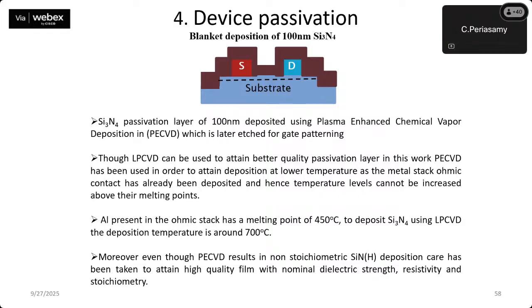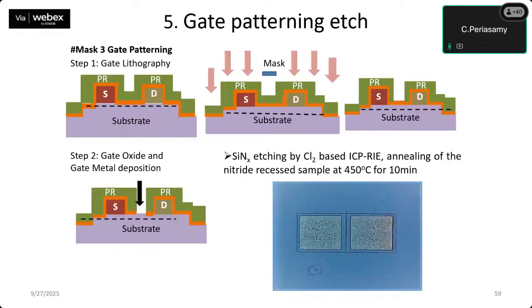So we have used that silicon nitride passivation layer, and the thickness of that passivation layer is 100 nanometer. As I told, we have used plasma enhanced, low pressure chemical vapor deposition, and we have used that plasma enhanced CVD technique to deposit that passivation layer. So this is the details of gate patterning.